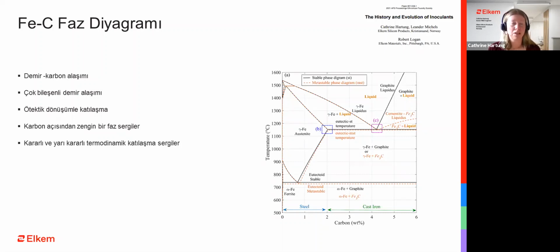So this phase diagram is actually representing two of the most common or most widely used materials in the world, cast iron and steel. The blue area is indicating the maximum amount of carbon that you can dissolve in the iron matrix, which is around 2%, while cast iron is typically the alloy from 2% up to around 4%. And then we come to the next point of interest in this phase diagram, which is represented by the pink frame, which is the eutectic point. And this is around 4.3, 4.2, depending on where they have taken their data from and how they have calculated or measured the phase diagram.